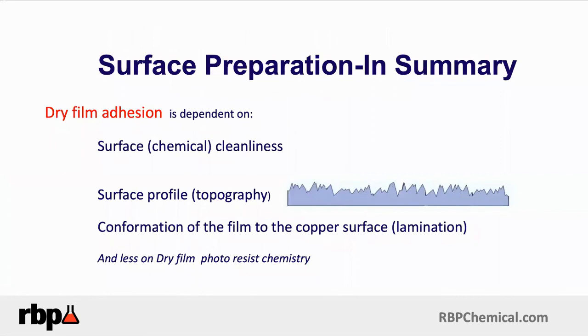So in summary, like I said, we don't have as much going for us today with dry film photoresist chemistry, because they have made significant improvements in the photoresist in terms of exposure and tentability and overall quality operations. They don't use as many adhesion promoter type chemistries to help you. So really, it's up to the fabricator to ensure you have a clean copper surface, you have a reasonably micro-roughened copper surface, some topography for the mechanical lock-in, if you will, adhesion, but not too excessive. And then for the lamination side, which again we'll talk about in the future, we want to make sure that the film does conform to the surface, which is again part and parcel to the lamination of the photoresist operation itself.